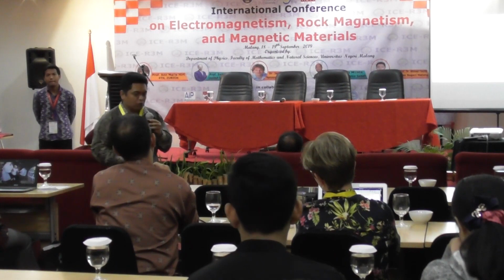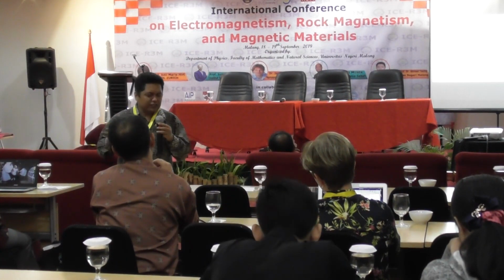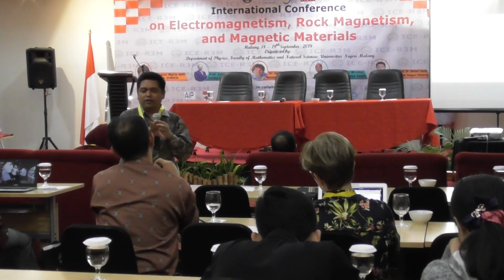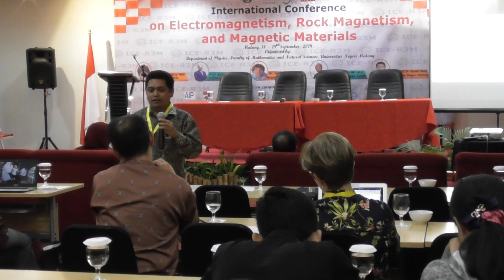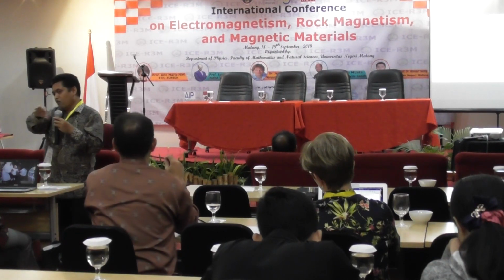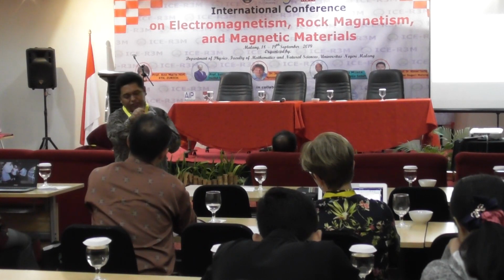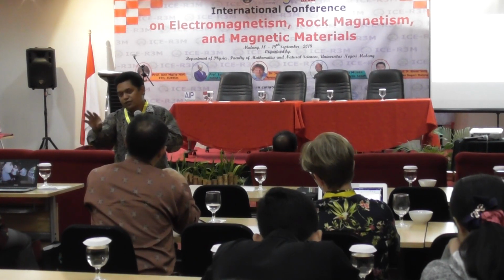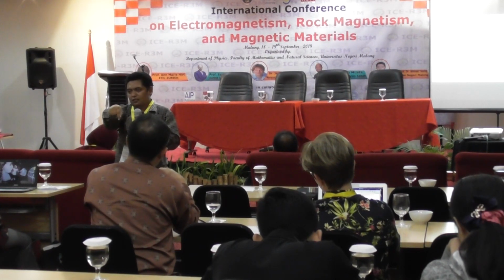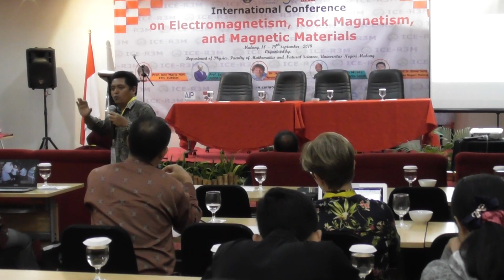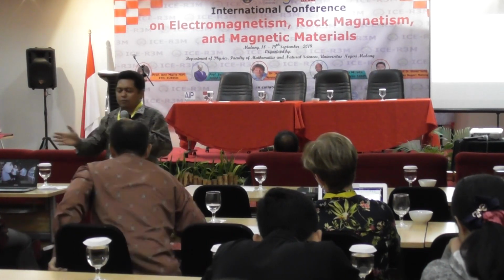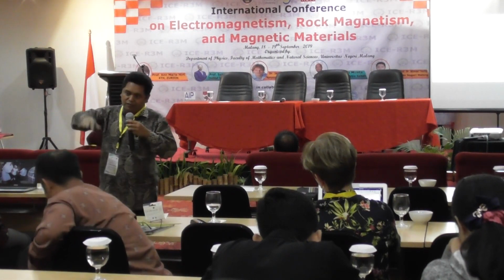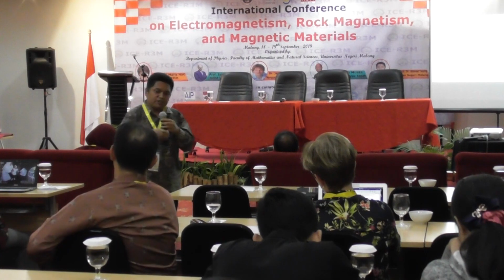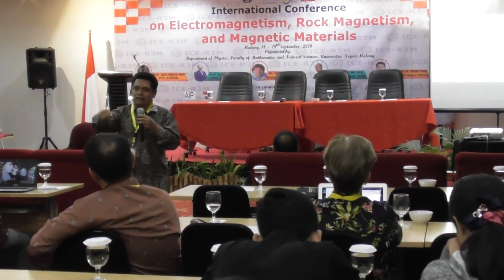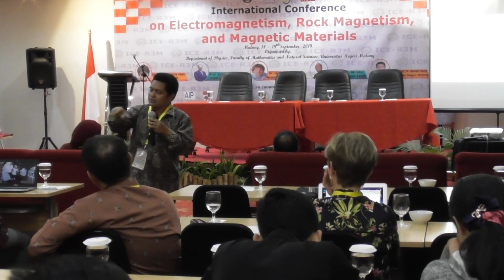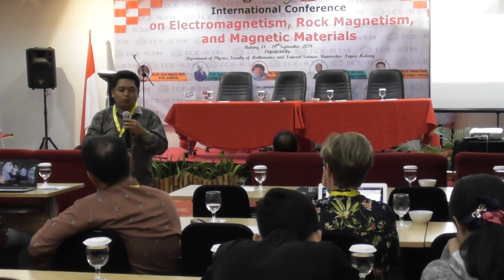And the second one is more powerful than co-precipitation. We also produce magnetic nanoparticle using a physical and chemical combination: co-precipitation and also ultrasonic treatment. When we have already produced the FeCl2 and FeCl3, we make co-precipitation in some reaction, and also we make treatment using ultrasonic with high frequency. So the larger particles will easily be removed, and we can take the magnetic nanoparticle as homogeneous particles.